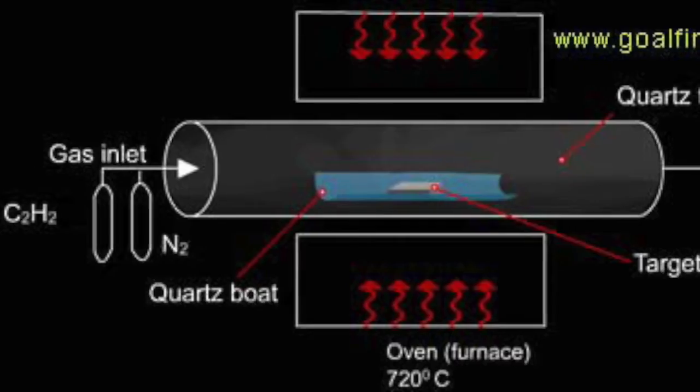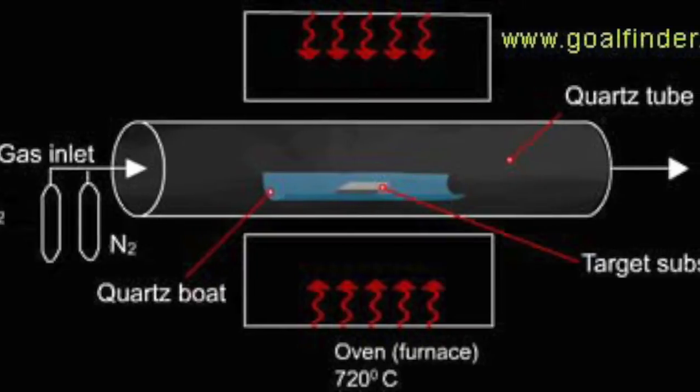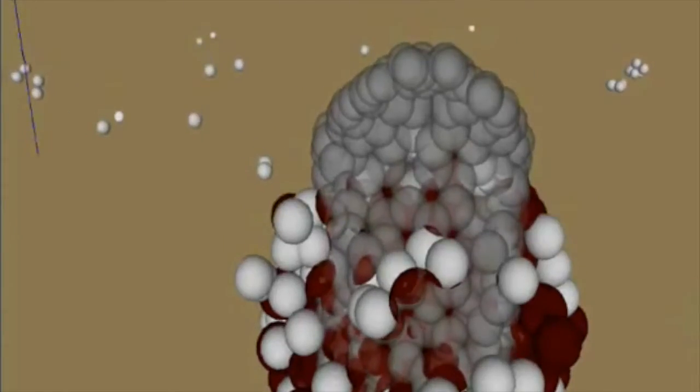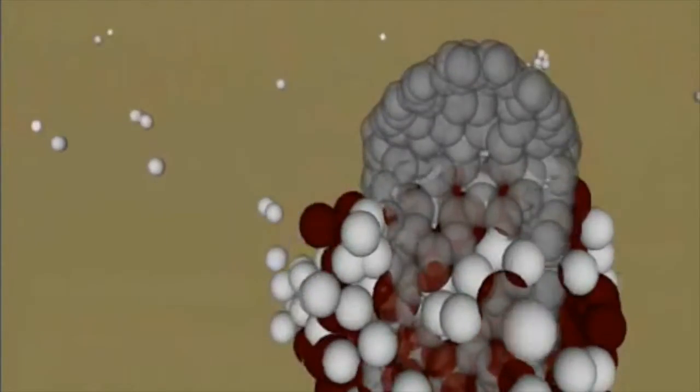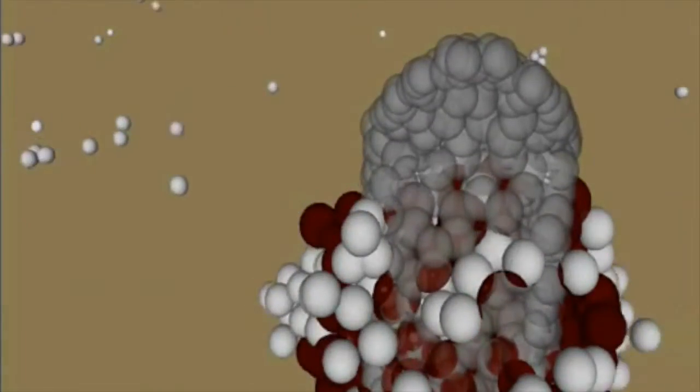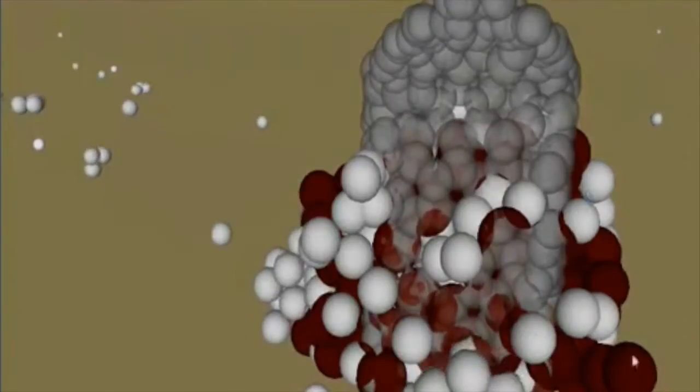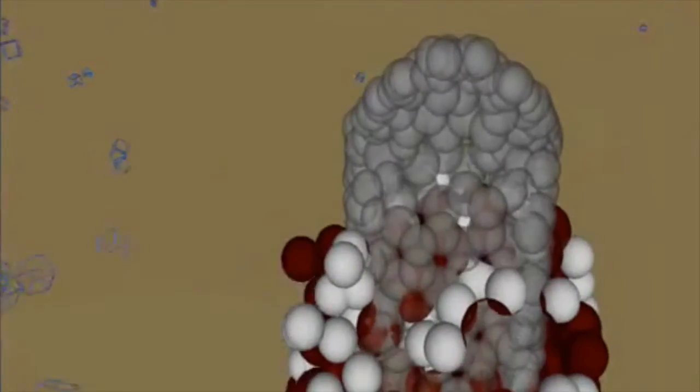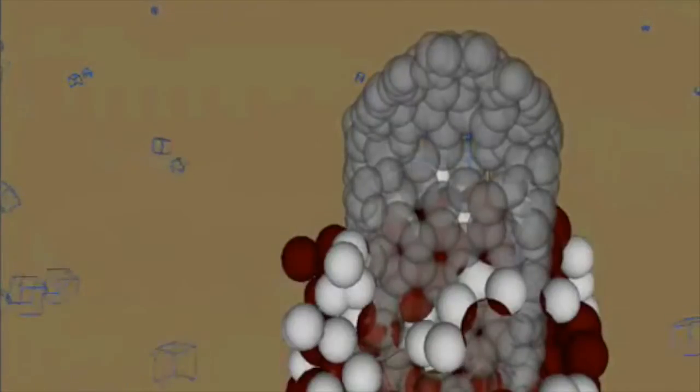We are going to specifically examine aerosol-assisted chemical vapor deposition, since it is the process used to produce the boron-doped carbon nanotube sponges. In this method, an energy source is used to break hydrocarbon gas molecules apart. The reactive carbon species then diffuse down to a substrate coated with metal catalyst particles, typically iron or nickel.